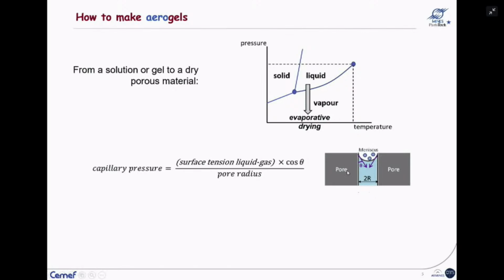This is a schematic presentation of the pore, with the material of the pore and the liquid which is inside. When liquid is evaporating, surface tension is created between the liquid and the gas. Then there is a contact angle, a meniscus, that is formed in the pore, and the capillary pressure also depends on the pore radius. So the smaller the pores, clearly the higher the capillary pressure. It also depends on the surface tension between the liquid and the gas. So if we want to make porous, nanostructured materials, clearly we have to avoid this capillary pressure.